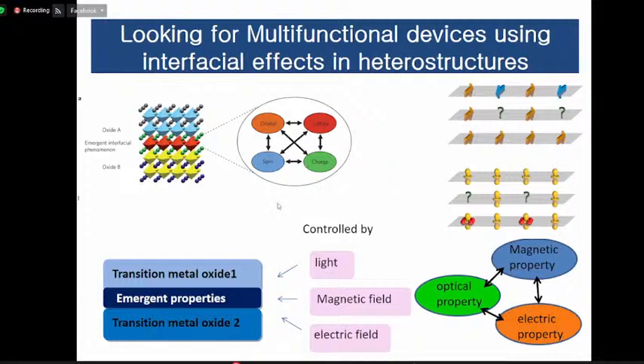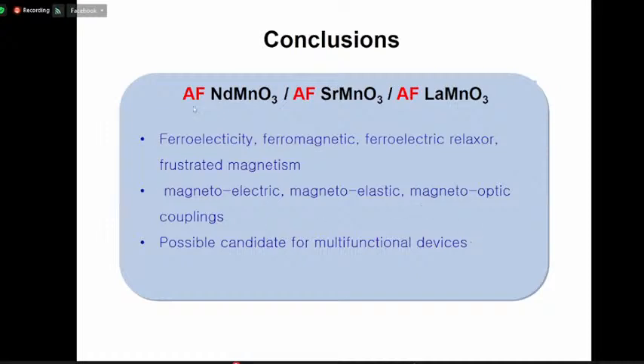Okay, until now we showed the emergent properties at the interface. Also, these can be controlled by light or magnetic field, sometimes the electric field. The properties are very close to each other, so you can tune some properties by another field. So we can design multifunctional materials using interfaces. Okay, this is the summary for my first material. We found ferroelectric, ferromagnetic, and ferroelectric relaxor and frustrated magnetism as well. We see magneto-electric, magneto-elastic, and magneto-optical coupling and magneto-orbital as well. So these kinds of materials can be used for multifunctional devices.